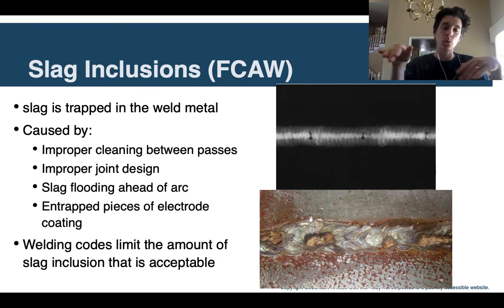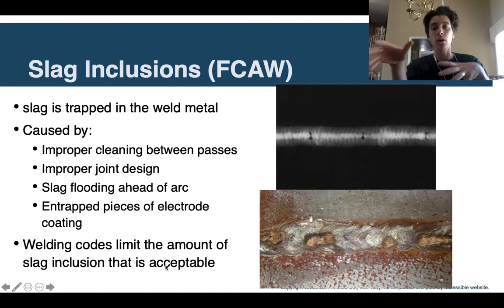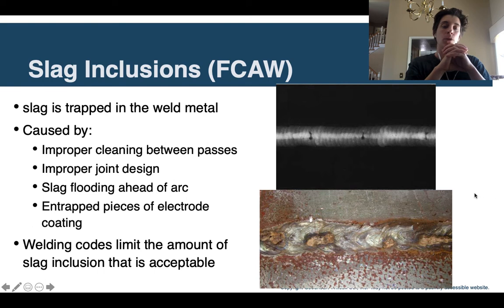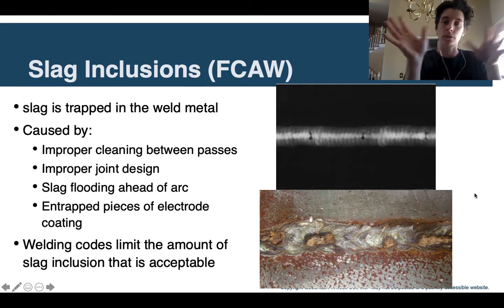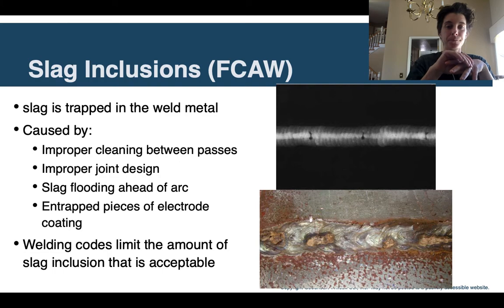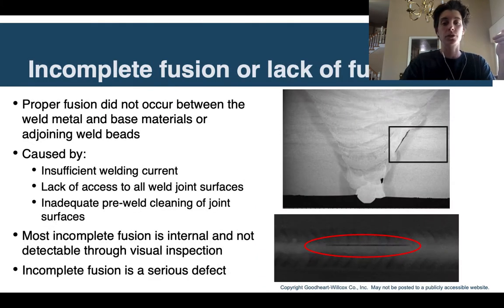So slag trapped in the weld metal can be caused by improper cleaning, a bad joint design, slag flooding ahead of the arc. So that would be something wrong with your setup or your process, or entrapped pieces of the electrode coating just coming off. There is some slag inclusion that is acceptable. Different welding codes will limit the amount, so you don't want something like this that's big and pretty major. But sometimes a little bit of slag inclusion is acceptable and will still pass inspection.